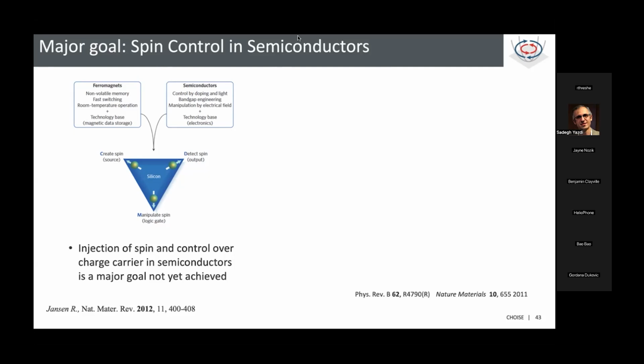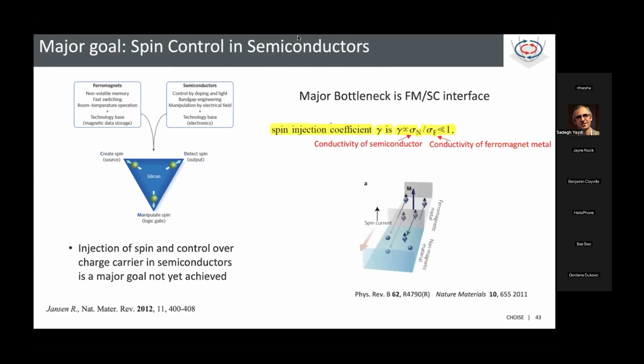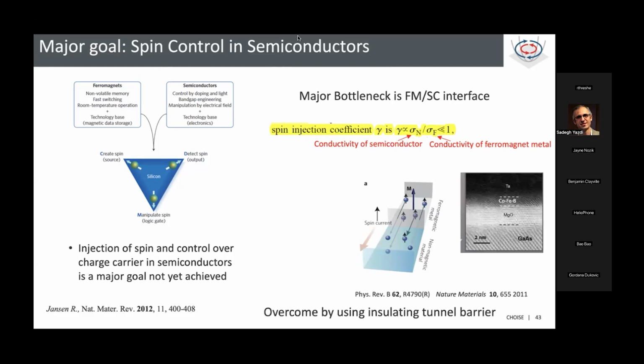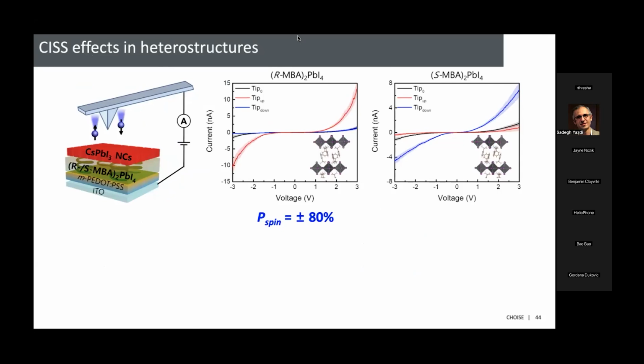But there's a huge barrier to this. This ferromagnetic semiconductor interface scatters the spin. So there's this well-known conductivity mismatch. You have a metal next to a semiconductor, try to inject spins across that interface, and it doesn't quite work. And so of course, this is what people are trying to do with these kinds of things. They put this tunnel junction in here. It has to be highly crystalline and so forth. This is quite an art, but it's great. It works.